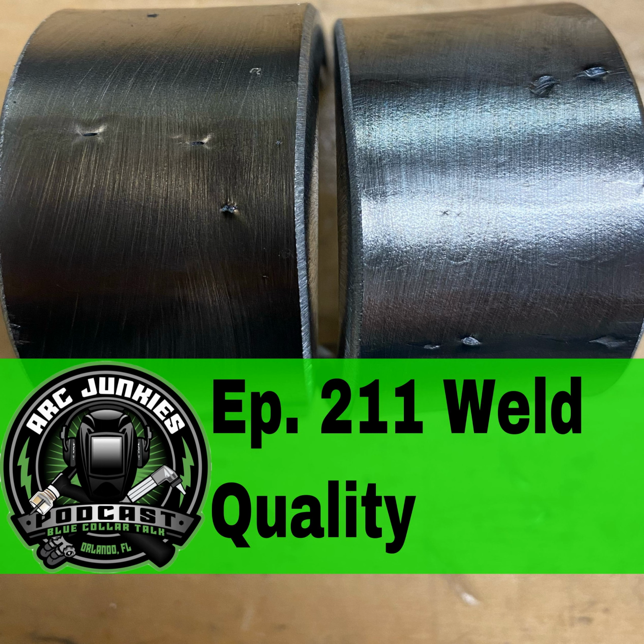Now, in addition to that, moisture on the joint surface. So if we have water or anything else on there, you might want to get rid of that. You can do that by heating up the base metal, not like a preheat or anything, just heating it up to dissipate any moisture that's on there. Also, you want to make sure that you don't have any moisture in your electrodes. And I talked about that in the Just the Tip Tuesday episode on what the F number is. We want to make sure that we're using low hydrogen electrodes. So we want to make sure that we don't have any moisture in our rods.